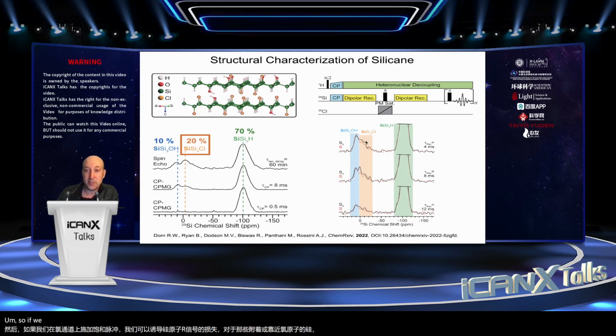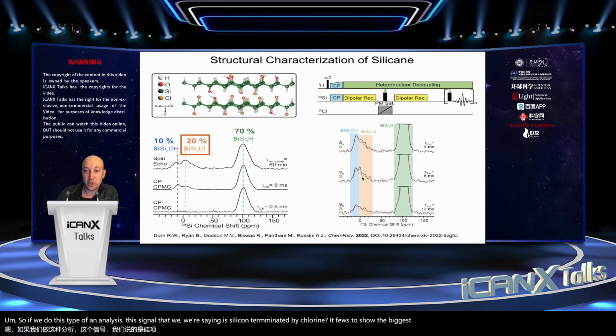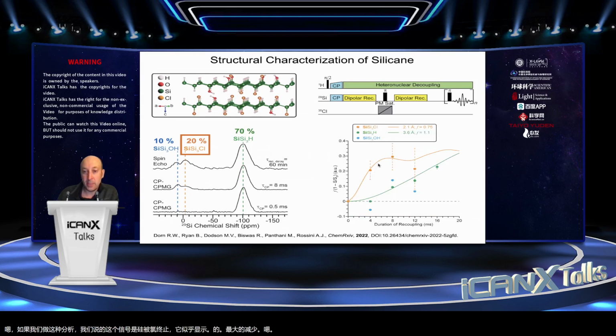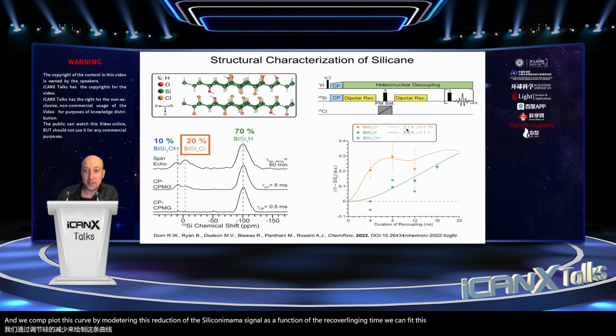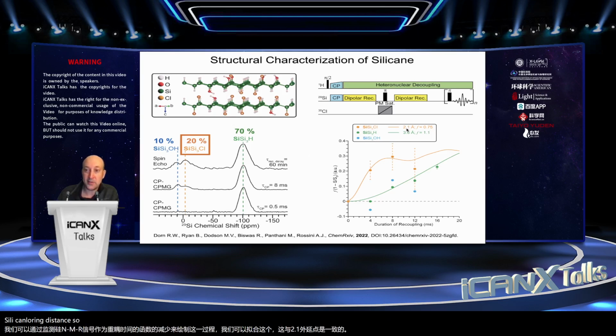So if we do this type of analysis, this signal that we're saying is silicon terminated by chlorine appears to show the biggest reduction. And we can plot this curve by monitoring this reduction of the silicon NMR signal as a function of the recoupling time. We can fit this, and this is consistent with a 2.1 angstrom silicon-chlorine distance. So this gives some good evidence for covalent chlorine in this material.